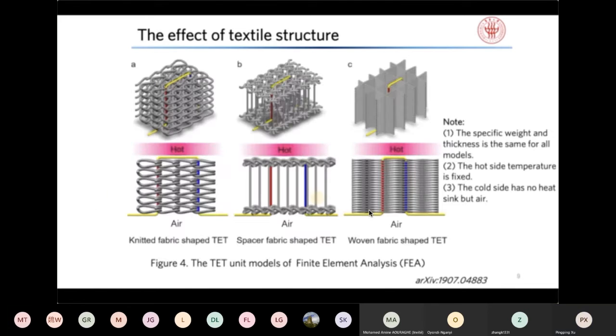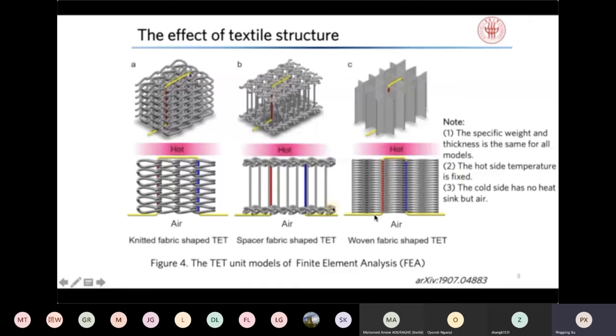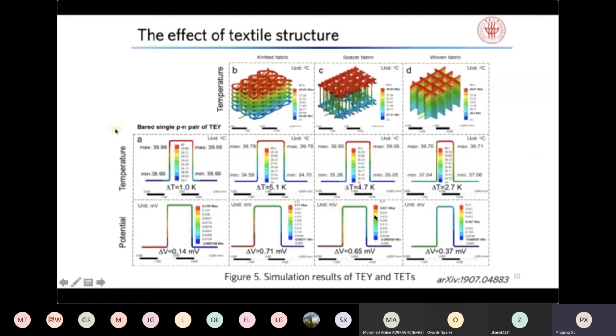And we then investigate the effect of the textile structure on the power generation, and we select three types of fabrics: the knitted fabric, the spacer fabric, and the woven fabric. And we use finite element analysis to simulate the power generation. And this is the main result. You can see that the bare single p-n pair of thermoelectric yarn can only generate a very small temperature difference. Then you have only a very small potential, the voltage difference. But for the three types of fabric, you can significantly enlarge the temperature difference between the top and the bottom surface of the thermoelectric generator.